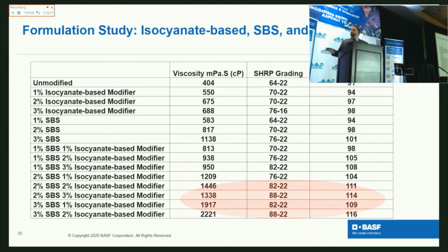Now, to touch on this a little bit, last week I decided to say, well, what's the extreme that I can take this? I don't have the data to share today because I didn't get it done in time. However, I did make a 94 minus 34 with a viscosity that was under 3,000. So the reduction in viscosity is amazing. Not really the reduction, but the lack of increase in viscosity. And again, that UTI increase is pretty amazing. And the other thing to note here is that with the SBS, in this asphalt, we were able to keep that minus 22.